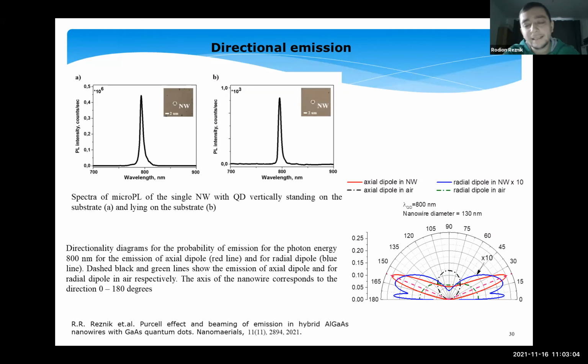These are new results, because for most applications, the directivity of emission is really important. In DTU as well, we have measured the PL intensity in different directions from nanowires standing on the substrate and lying on the substrate. And we have found that the PL spectrum peak from the standing nanowires is, I think, two orders of magnitude higher than from the lying ones.